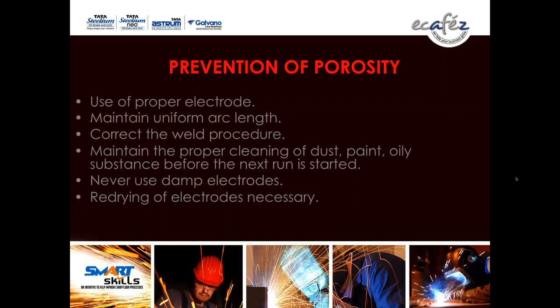And prevention of porosity: use proper electrode, maintain uniform arc length. As I said, the ideal arc length should be 2 to 3 millimeters. Correct the welding procedure, maintain proper cleaning of dust, paint, oily substance before the next run is started. Never use damp electrodes. Re-drying of electrodes is necessary. So these two are the rounded welding defects. They can be exempted to some extent, but no linear welding defects are permitted in welding.